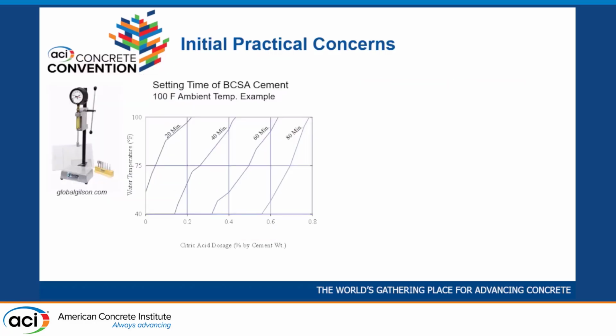So from our work at Arkansas, I thought I would start out with some practical mix design concerns. Obviously, mix design is important for casting structural elements. We need mixes that have the properties that we need to satisfy our structural requirements. So one big thing is setting time. At room temperature, the cement will set up in like 10 to 20 minutes with no retarder, so we generally always retard it. We've also found that temperature is an accelerator of setting time, so at higher temperatures, the cement will set up more quickly.